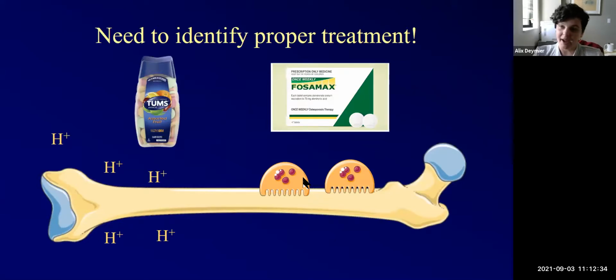So if I just have acid that's coming in and dissolving my bones, I'm just going to give my patient Tums. This is literally our treatment, is we just fill people with carbonates. Give them Tums, hopefully it brings down their acidosis. You've eliminated the acid stimulus, and therefore you don't have dissolution. That would be the fastest way to treat it if the physiochemical response is really the cause of dissolution.